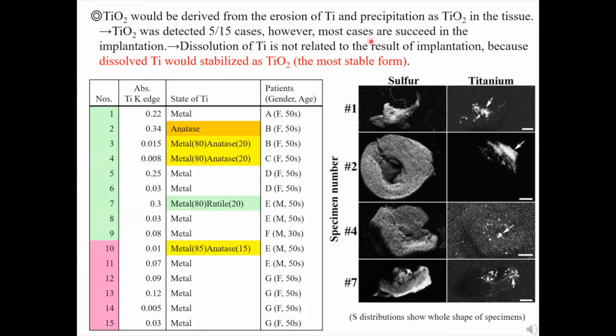In all 15 estimated cases, we detected metallic titanium or titanium oxide. However, most cases were successful in implantation. Therefore, this accumulation of titanium would not affect implant stability. Because both metallic titanium and oxide are chemically stable solids, a negative effect would not occur in the surroundings.